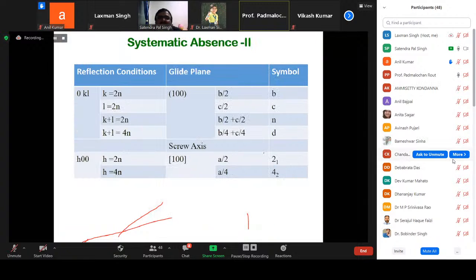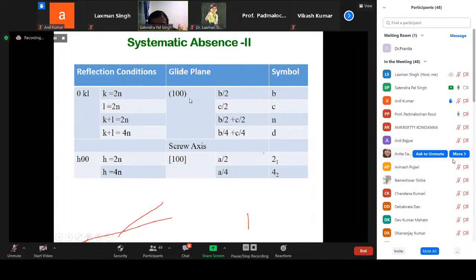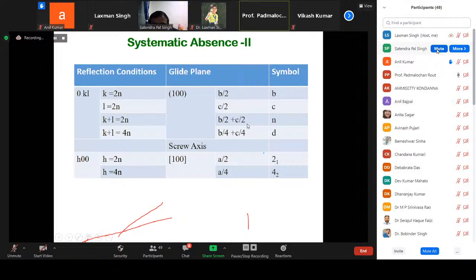Then comes whether there is any translational symmetry, whether there is any glide plane or any screw axis. For knowing that, if K is even, there is a glide perpendicular to 100. So the translation is b/2. If L is 2n, the glide plane is 100 and the translation is c/2. If K plus L is equal to 2n, then the translation is b/2 plus c/2. If K plus L is 4n, then b/4 plus c/4. This is called the glide plane. This is a diagonal glide. This is called a diamond glide.